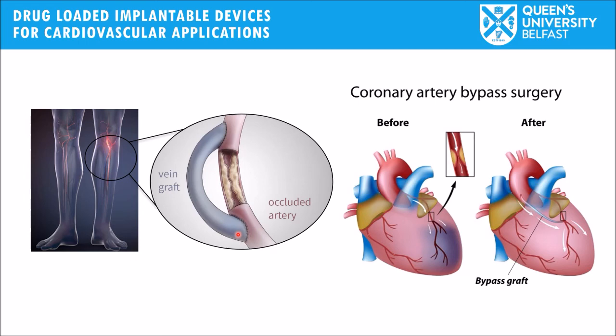But the use of small diameter vascular grafts, smaller than 6 millimeters in lumen, can be problematic, because these grafts tend to be blocked. They can be blocked because of the buildup, for example, of platelets that attach to the surface. This happens especially, as I mentioned before, in synthetic vascular grafts. So there is an interest in developing